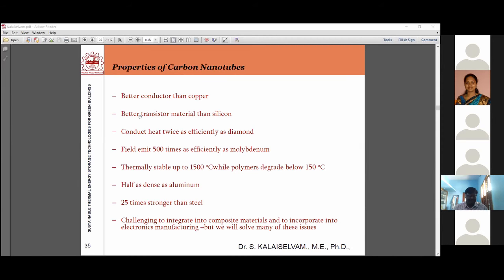For heat conductivity, immediately we say diamond, but carbon nanotubes conduct twice the heat compared to diamond. Field emission is 500 times as efficient as molybdenum, and carbon nanotubes are also stable up to 1500 degrees centigrade. For aircraft applications, they use aluminum because it's a lightweight material. As far as carbon nanotubes are concerned, they are half as dense as aluminum.